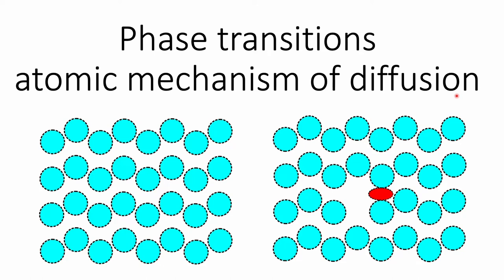When we handle a solid there is a nice sensation of rigidity, which implies that the atoms within are packed together and well bonded. So it becomes difficult to imagine how an atom could actually move through that solid — it would have to squeeze through narrow gaps between atoms and find a location where it is comfortable to sit. This squeezing process leads to local distortions, and therefore there is a barrier to the movement of atoms, an activation barrier.